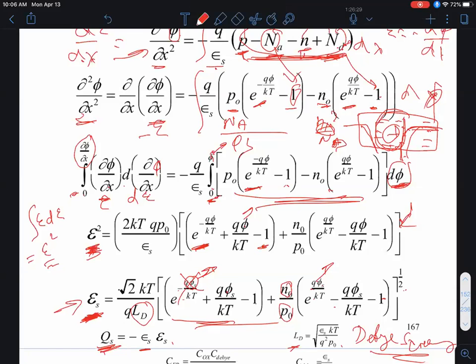So under these conditions, then, you'll get a potential V of R, which is not simply Q over R, but Q over R e to the power minus R divided by the screening length, L_D, as shown over here. And as you can see, that depends inversely on the carrier concentration, n naught or p naught. Now, what did you expect if the carrier concentration went up? Would the screening be more or less effective? Clearly, it'll be more effective, right? Because if you have more mobile carriers that can crowd around, it'll screen out the effects earlier, right? Therefore, the screening length, which is the length scale needed to screen out these charge imbalances, would be reduced, okay? And it turns out, if you go through the math, the screening length appears over here. It's an important concept.